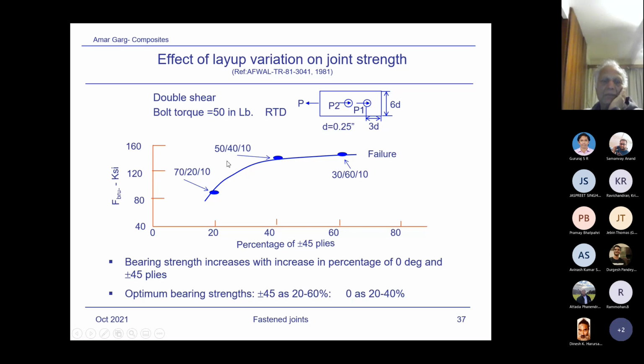And what you see from here, that means there has to be some balance. Reduce the number of zeros, increase 45s, and that improves the performance significantly, as you can see. And if you increase further the number of 45 plies, then your strength slightly increases further. But between this one and this one, there's not much improvement. So what it says, and I'll show you one of the diagrams where we are trying to show the various important layups which you need to consider for the joints. There would be around 40 to 60% 45s for a good joint design.